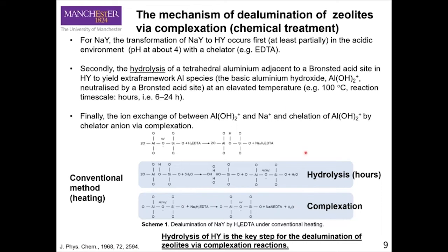But the main issue is, after detailed analysis of the mechanism, we found the complexation steps for dealumination to create a hierarchical structure have 2 steps. The first one is hydrolysis, which means we have to work with water and hydrolyze the framework structure to lose the framework aluminum. Accordingly, the complexation would chip in to try to remove the framework aluminum.